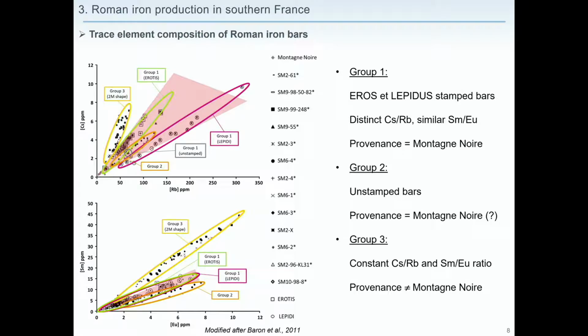So we can find different groups. A first group containing the Eros and Lepidus stamped bars, and also an unstamped bar here. They have distinct cesium to rubidium ratio, but similar samarium to europium ratio, but always included in the variation range of materials from the Montagne Noire, here and here in red. So the authors conclude to a provenance from the Montagne Noire for these bars.